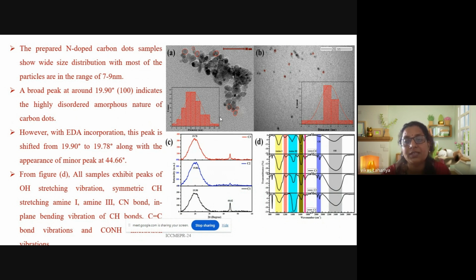There are two different samples with different amounts of EDA. Sample A has a small amount of EDA, while sample B has a larger amount of EDA, that is, the content of the dopant ion is relatively large. So sample B has a smaller size compared to sample A. And from the XRD, a broad peak around 19.90, approximately 20 degrees, indicates the graphitic 100 plane. And this represents a highly disordered amorphous carbon core.